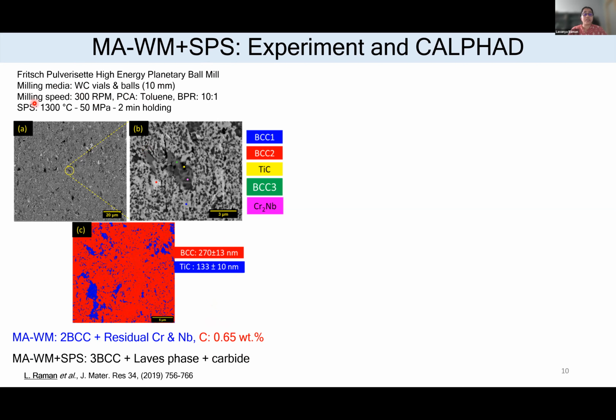After we sinter them at 1300, we have this kind of a microstructure, where you can see different contrasts. With the help of EDS, we were able to identify these phases. In total, we have 3 BCC phases, titanium carbide, and Cr2Nb Laves phase as the secondary phase. In the 3 BCC phases, the lattice parameters are very close, so we couldn't resolve them.